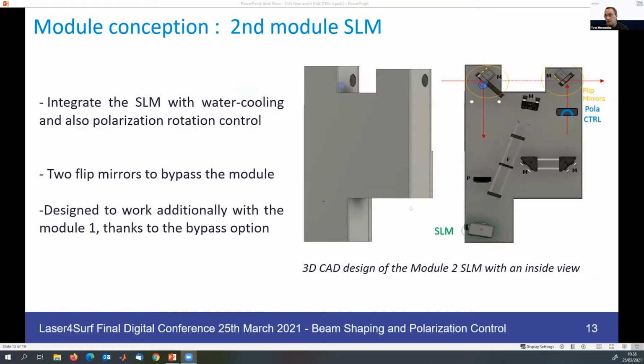This is a design of the SLM module. You see it's larger than the one with the DOE. Inside of the box, you have 2 flip mirrors at the entry that permit to bypass the SLM, and then you can leave the SLM fixed on the laser micro machining system, and then you can easily switch from the use of the SLM to the use of the DOE that will be placed afterwards on the beam line. So the first mirror will just reflect the light to the SLM, with afterwards a second mirror and a polarization controller at the end, just before going back to the original beam direction to the scanner.